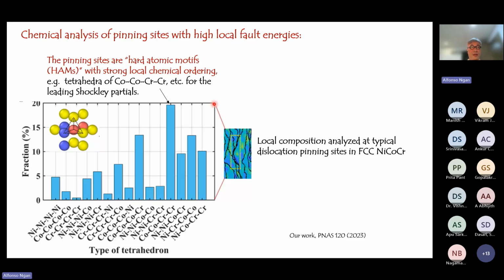And there are other evidences in other systems. So in this case, we have the cobalt, chromium, nickel system, where the stronger pinning points would correspond to some special atomic clustering, such as clustering where you have more cobalt and chrome pairs. So these are, of course, down to very localized chemistry that are the pinning sites.